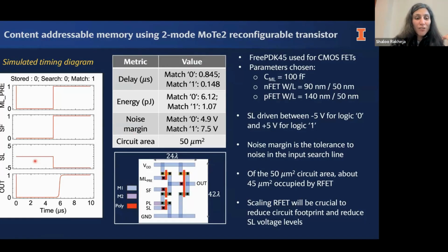You can see that the search line voltage goes between +5 and -5. That's not really ideal. We want to be able to search within 0 to 1 volt, which is compatible with the silicon technology. The circuit area is 50 microns. It's huge, so we want to be working on scaling this device. In fact, we have a paper coming out hopefully soon, which talks about how much benefit we would get if we did scale this RFET.